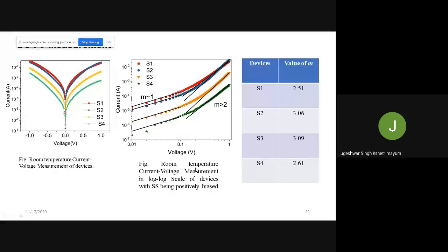What we found here is very interesting. Now here is the IV curve. This is the measurement. We measure IV from -2 to +2, but we are showing the data for -1 to +1 here. But in this one, you see the curve patterns. The patterns are not similar. What does this mean? It is asymmetry. A small asymmetry is because when we make the contacts, we are making steel, polymer, and silver. The work function or barrier height of the silver and the polymer, and the barrier height of the steel and the polymer, are not equal. So the injection rates are not the same. It is showing here.